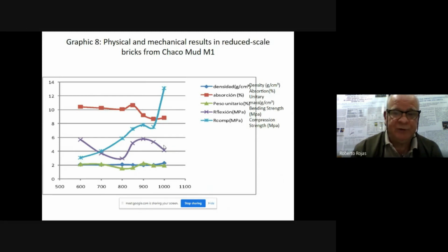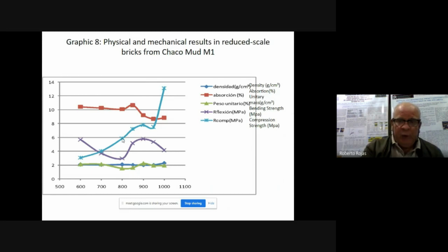So we have an absorption about here, up here to 850, more absorption. But the bricks are made about Chaco mud here, 750 or 800 degrees centigrade. So here we have a good compression, more than 6 megapascals, and these are used to produce the bricks.